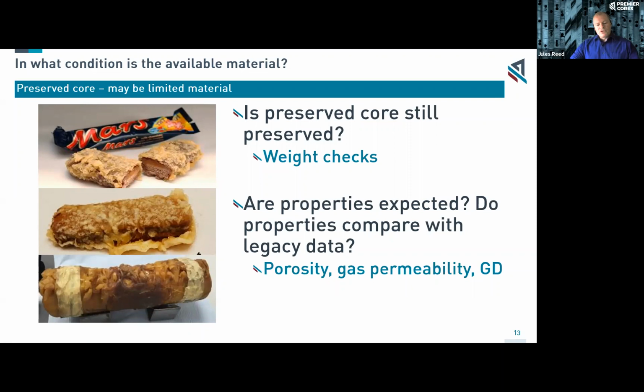Once we've obtained samples from that, and this could be a whole core sample, or it could be a preserved core plug sample, one inch or 1.5 inch, once we start preparing those samples and we do cleaning, or we make some measurements of porosity or permeability, we should compare those properties back to our legacy data. Are the properties equivalent to our legacy properties? If not, then our samples may have changed over that time. If they're equal, then there's a good chance that we've got a sample that is usable. I've known samples that have been used 20 or 30 years after they were originally obtained from a coring process.